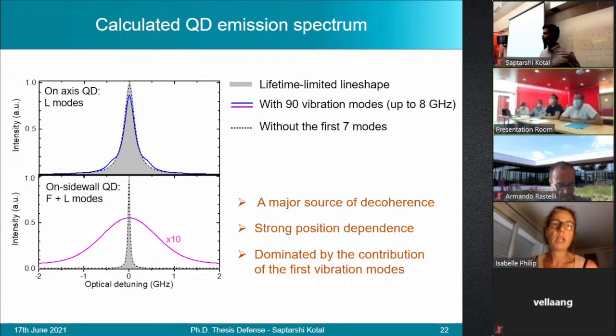Or you didn't do the experiment? I haven't done the experiment myself. But such a measurement of lifetime was performed in the course of the work that I presented earlier, by Munch et al., in the group of Richard Warburton. I have not measured to see if it corresponds to this, but what they find goes quite well with our calculated results.